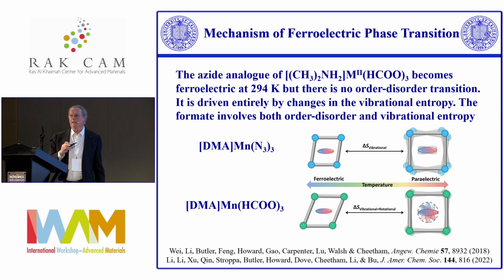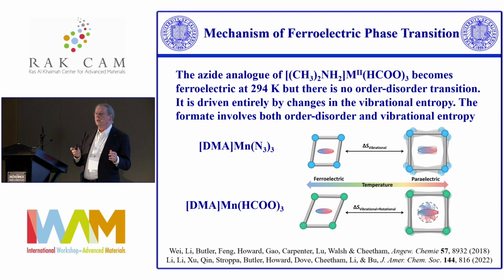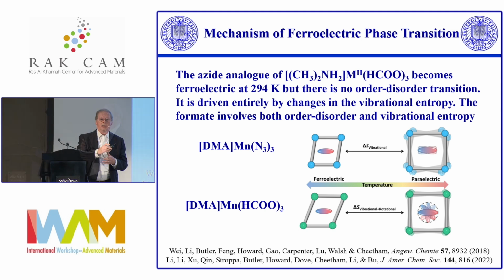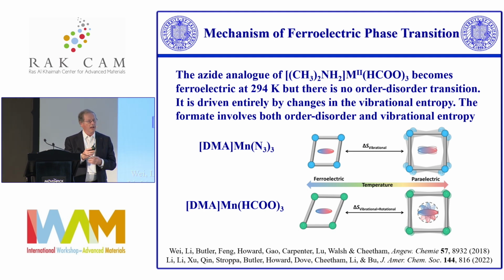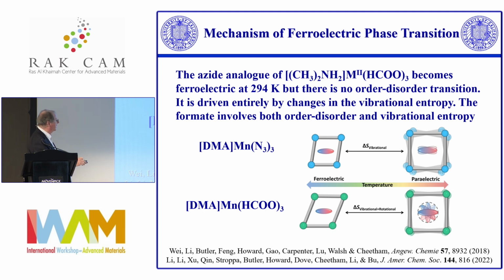If you look at the azide analog, which we also studied, so here's the azide analog, there's a phase transition to a ferroelectric phase on cooling, but even with DMA cation, there's no order-disorder transition. And so the transition is driven by changes in the vibrational entropy of the structure. And people ignore vibrational entropy, but it's a very important component of the phase transitions. And in this case, it's the only contribution to the phase transition, to the ferroelectric one. Whereas in the formate case, which we also studied, of course, you have both a contribution to the entropy change from the order-disorder of the cation as the cation locks into a specific position, and you have a concomitant change in the vibrational entropy of the lattice itself, the framework itself.